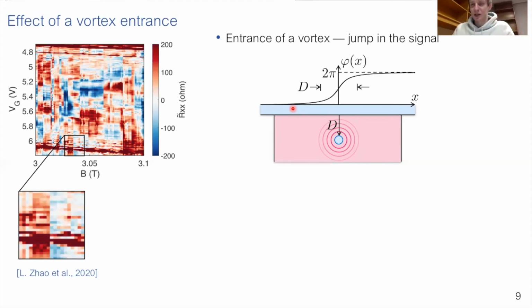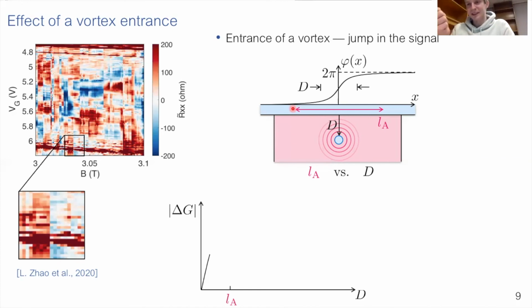But what can we understand about these jumps in the conductance? Of course, the magnitude of the jumps is determined by the distance for which the vortex has entered. And what we need to compare this distance to is the Andreev length, because it is essentially the single length scale in our problem. So the jumps are determined by the ratio between the Andreev length and the distance of entrance. If the distance by which the vortex has entered is much smaller than the Andreev length, then the jump is small. Basically, the kink gets very sharp, so it's 0, 0, 0, and then almost immediately 2 pi, 2 pi, 2 pi. So this almost does not affect interference except for a very narrow window.